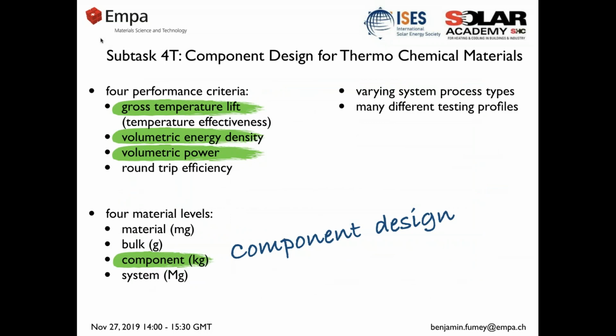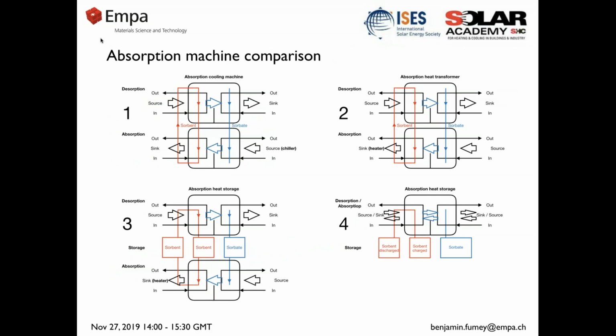Now, with this in mind, going to component design, in our liquid absorption heat storage, we find that this is a similar process as, for example, a chiller or also a heat pump, absorption heat pump. Nevertheless, with including the storage, in other words, the storage of concentrated sorbent and sorbate in charged state, and then in discharge state storing of the diluted sorbent for recharging, we have a process where we need to be able to reach this maximum discharging in a single pass of the sorbent through the heat and mass exchanger.